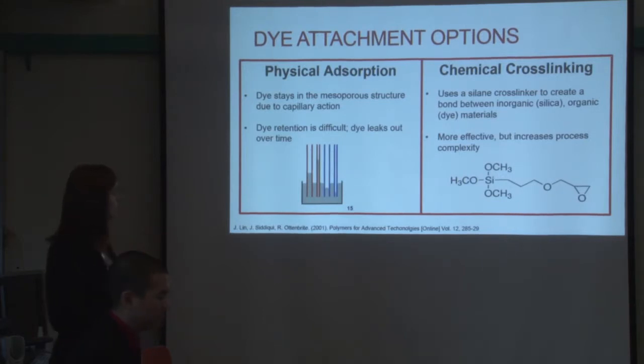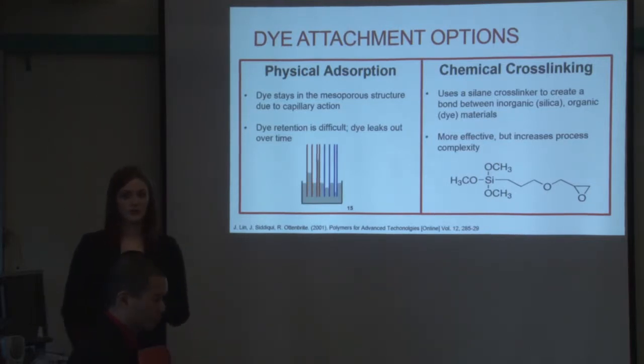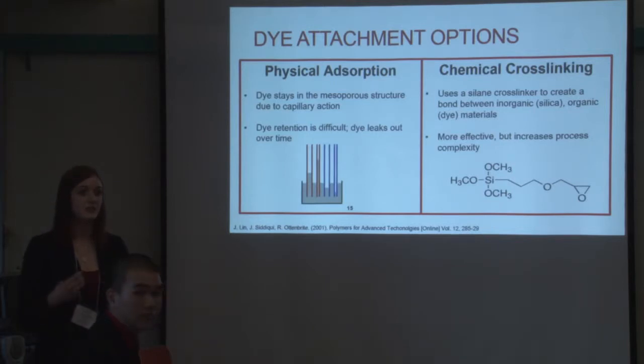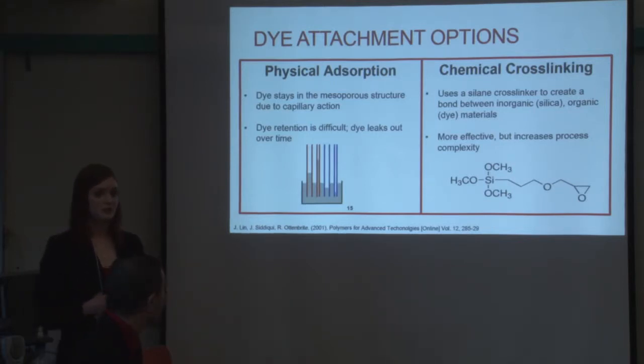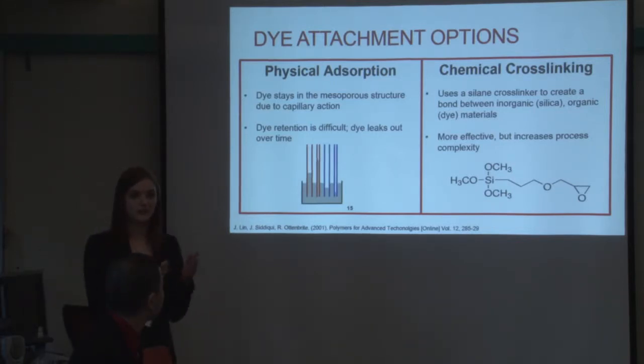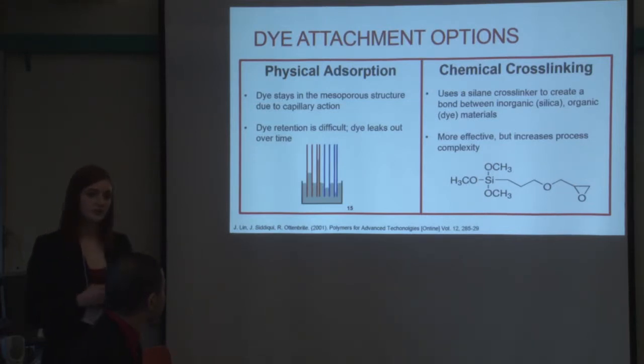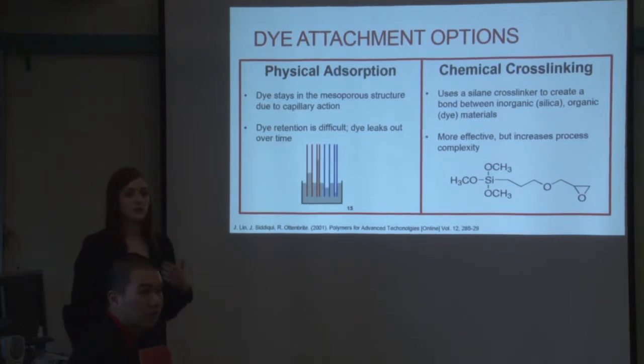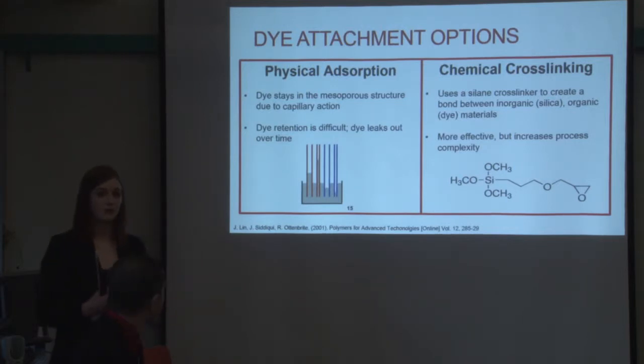So these were the two options that we considered when determining how to attach dye to our particles. The first thing that we considered was a physical adsorption method. We could basically have the dye in a solvent and evaporate the solvent off, and then we'd just have dye physically impregnated in the particles, or into the pores, sorry. But the biggest problem with that is dye retention becomes a difficulty. Over repeated washings, even when preparing the dyed particles, we noted that there was a loss of color.